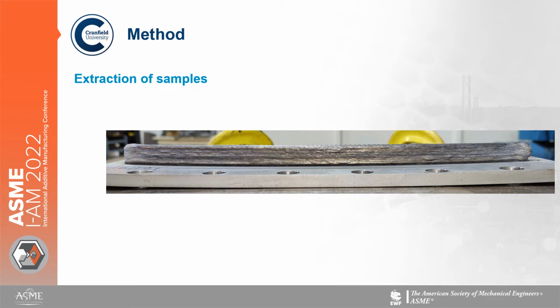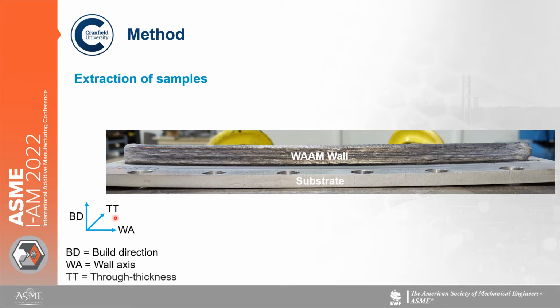So after our walls were completed, we needed to extract some samples. So we used a short wall approach for this because we only need 3 samples to get a good average for our tensile properties. So as you can see, here's our WAAM wall, which is sitting on top of our substrate plate. We also have 3 axes that we're going to refer to in the following micrographs. So first of all, we have our build direction, BD, which is the height of the wall. And we also have our wall axis, which is the length of the wall. And we also have our through thickness, which is the thickness of the wall.